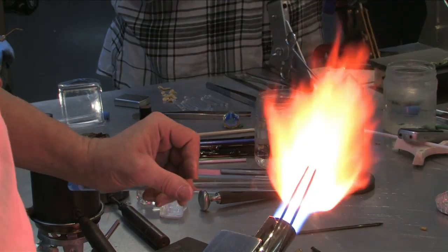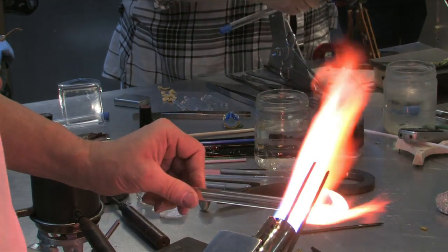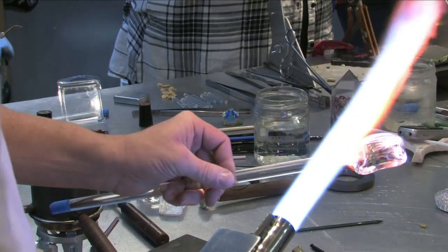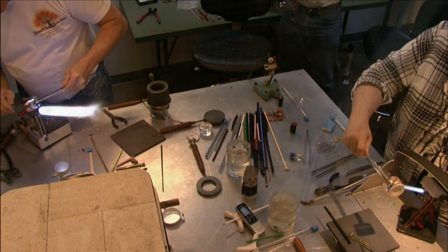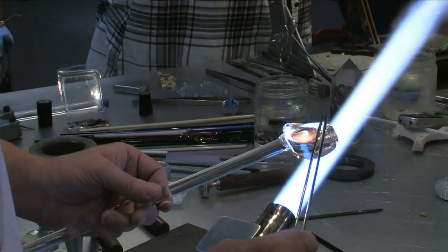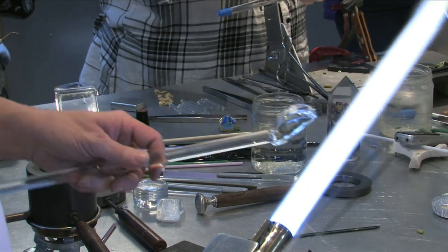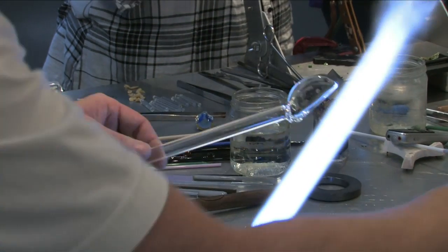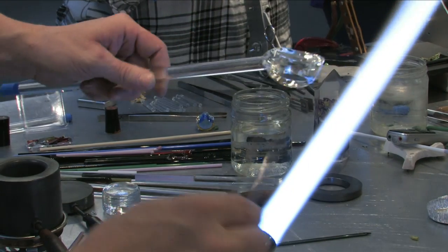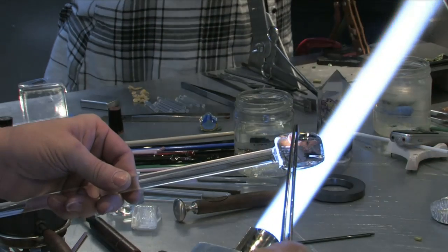And now miter the sides. Both of them. And then the flat sides. Both of those. By the time you peel this thing, it should still be in that half a puck shape. That means that you managed to keep the core solid, which is what you're supposed to do. If it's already melting and falling and getting out of control, then you're doing it out here. If you're doing it out here, you're lost. You're never going to get this thing peeled in a pretty fashion, and you're never going to get total control.